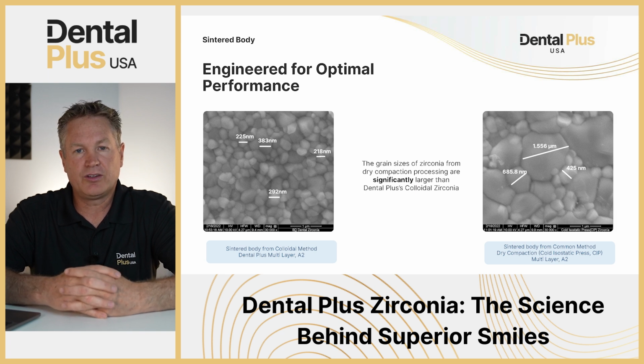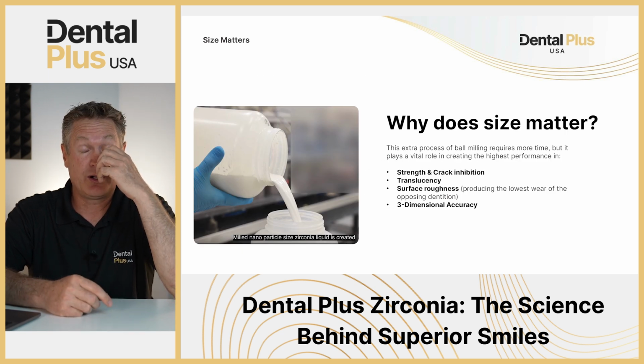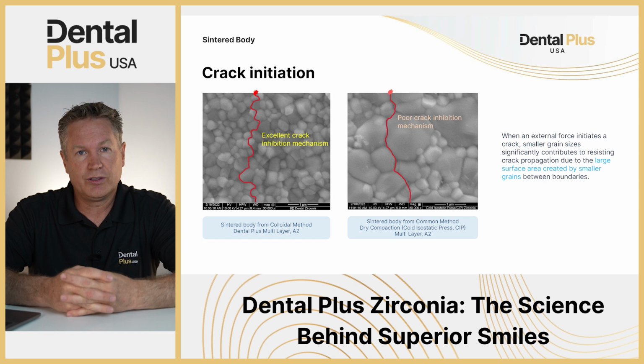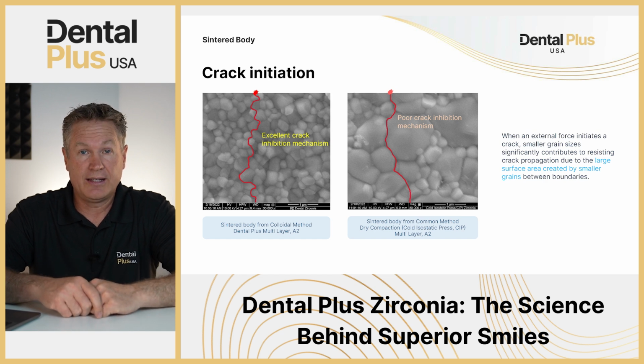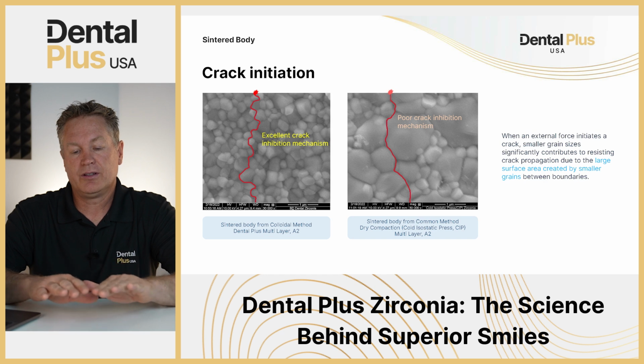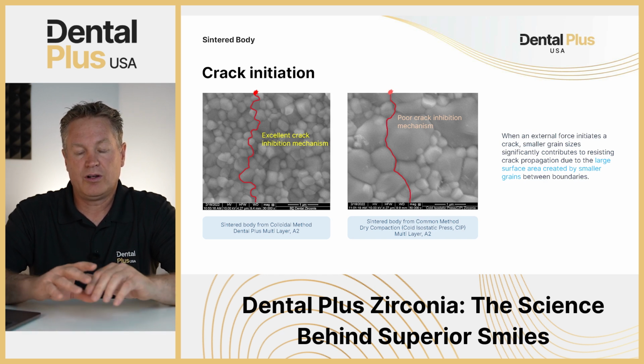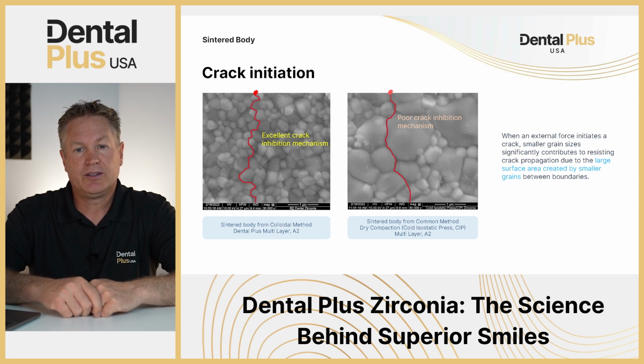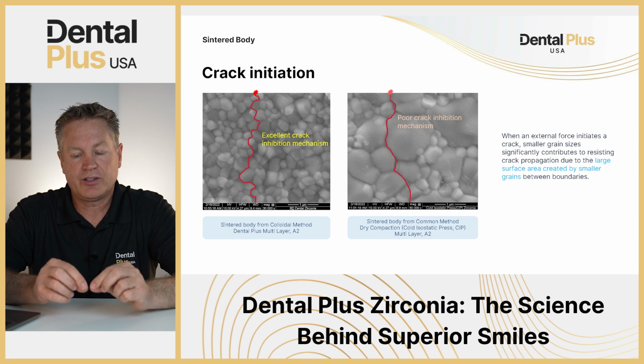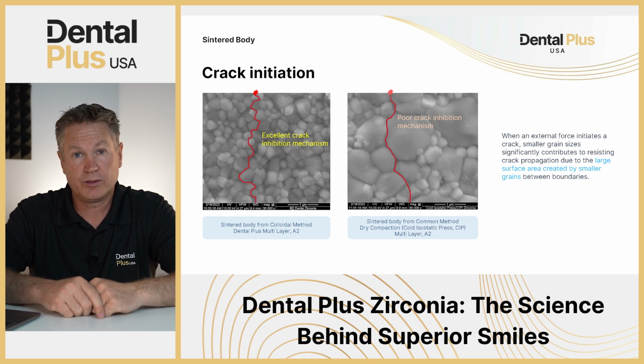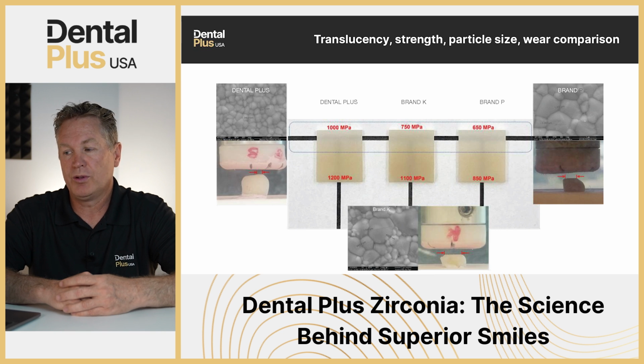So in that way you have irregular size particles, and then they're usually much bigger size particles. So basically what that does is it's not quite as good. When you have a colloidal method where you break the particle size down and you have them all very similar in particle size, and then they all lay out homogeneously as they're poured and dried in these molds, when you have this homogeneous layer of all the particles laying out very, very uniformly, it's much better as far as crack propagation. So when you have a little tiny crack that starts, it's not going to travel very easily through those small particles, whereas when you have bigger size particles, the crack will much more easily travel and propagate through the material than it will with the smaller size particles.